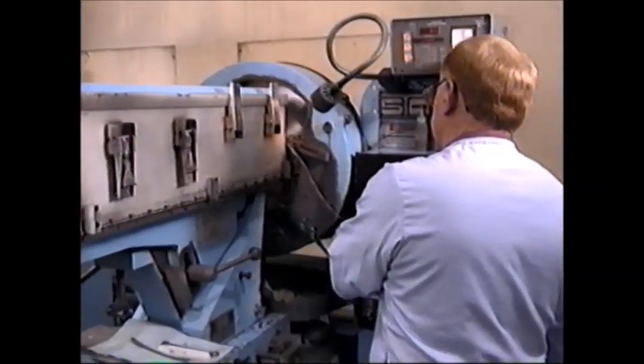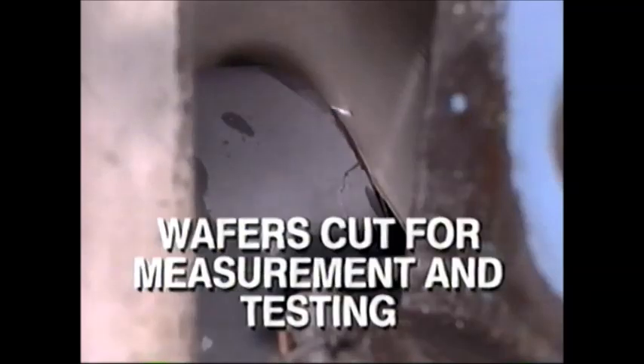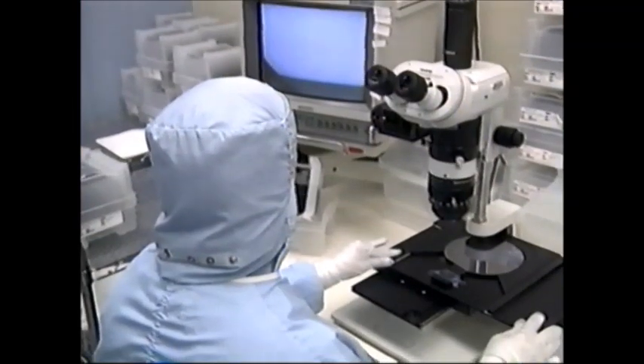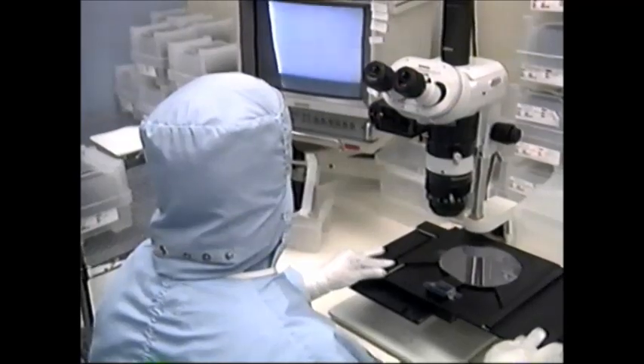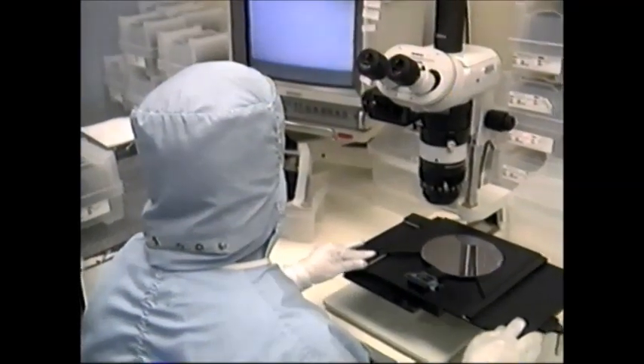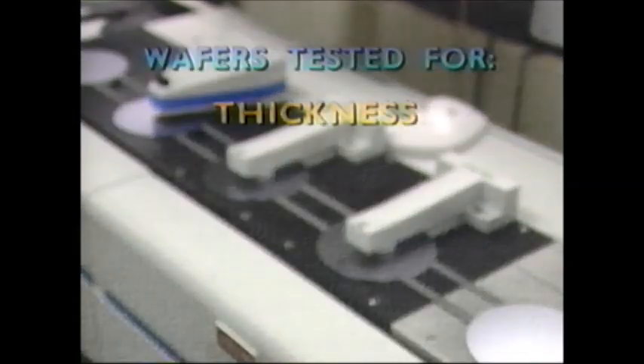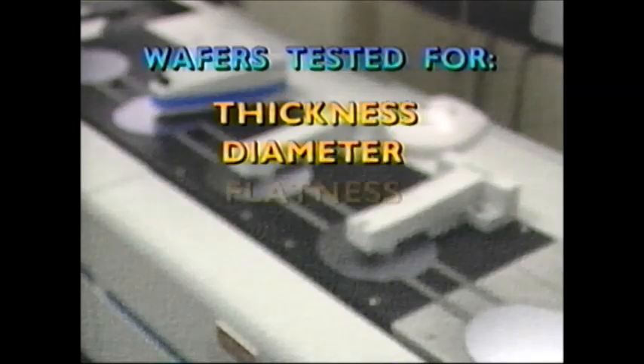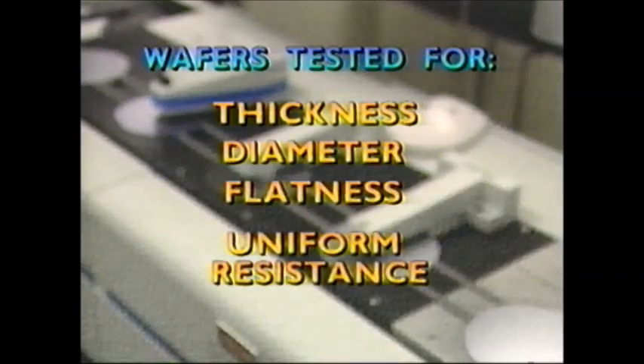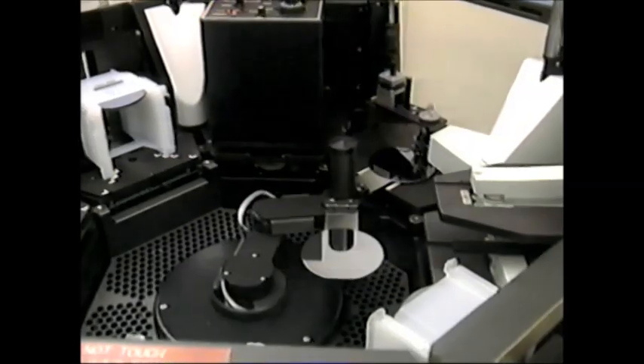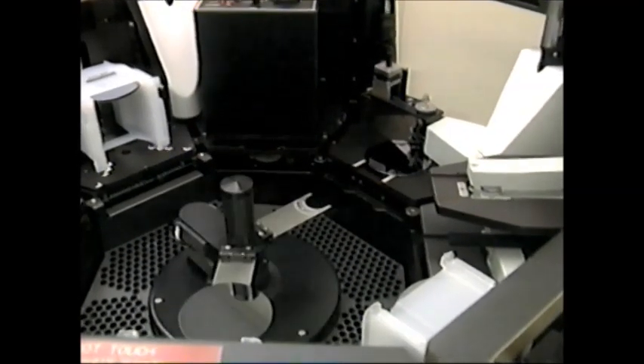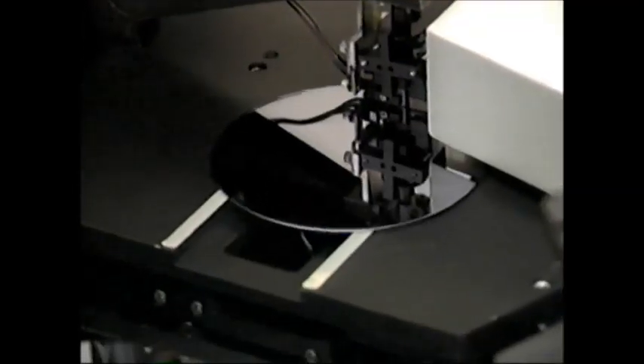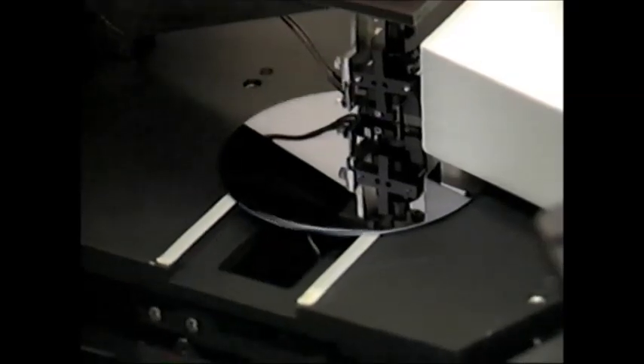Next, the ingot is placed in a diamond saw and a few wafers are cut for measurement and testing. All wafers undergo stringent testing throughout the manufacturing process. Factors such as thickness, diameter, flatness, and uniform resistance are constantly checked against specifications. Tests for characteristics such as resistance are performed using a non-contact resistivity probe.